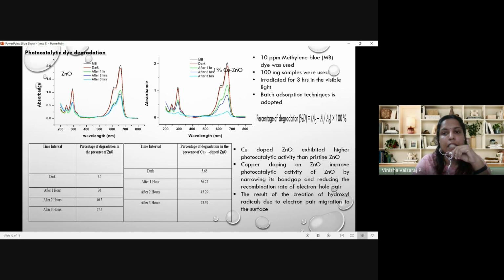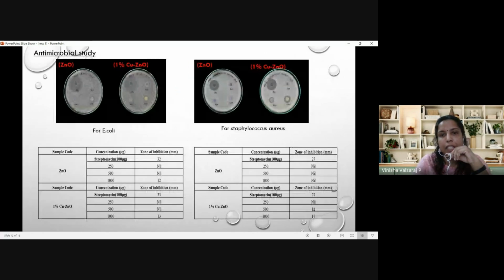And this is the equation for finding the percentage degradation. Using this equation, we found the percentage degradation ability of ZnO and copper-doped ZnO at different time intervals, and we see that copper-doped ZnO has a high percentage of degradation. Mainly it is because, while doping with copper, the band gap is narrowing. This was also already confirmed in the Tauc plot, and that reduces the recombination rate of electron-hole pairs, and also leads to the creation of hydroxyl radicals due to the electron-hole migration to the surface.